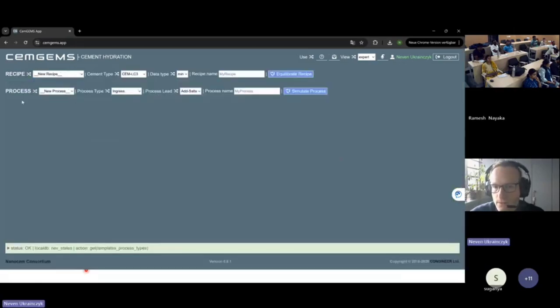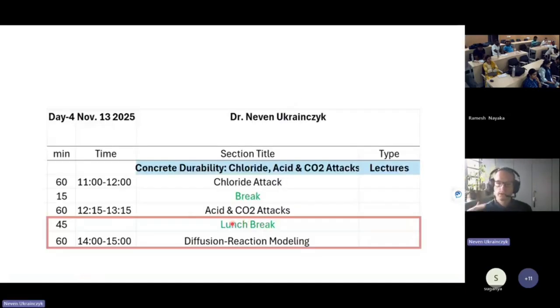So simply by this process, you can again simulate all these minerals, also aluminate cement, the LC3 system, and then you can add here leaching or ingress. You can define the salts and just simulate, and you can get a nice thermodynamic prediction of the leaching and also the chemical attacks. So we have two things for the demonstration: the Python, how you can model the diffusion, and also how you can model the chemical attack in a thermodynamic model. So now I'm open for questions.